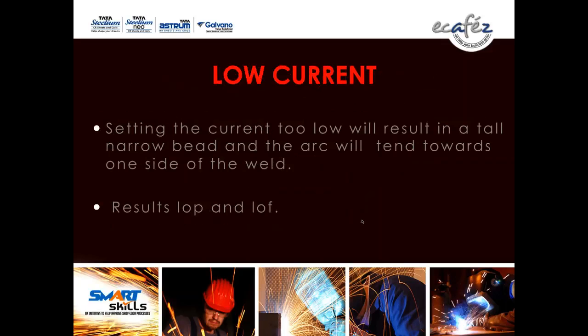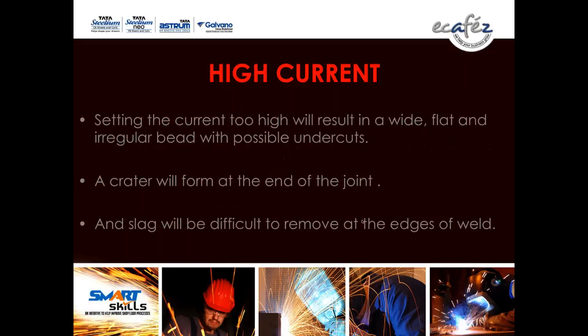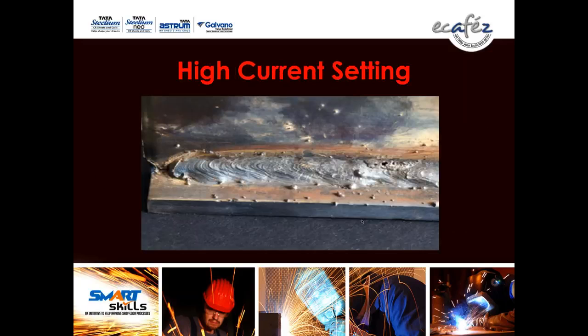Too low a current setting results in a narrow bead, and the arc will tend towards one side of the weld. The result is lack of penetration and lack of fusion, LOP and LOF. Too high a current setting will result in a wide, flat and irregular bead with possible undercuts. A crater will also form at the end of the joint if you set the current in high mode, and slag will be difficult to remove at the edges of the weld. See the pictorial view of high current setting by MMAW, with maximum spatters, undercut, everything.